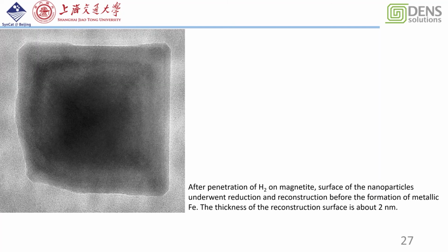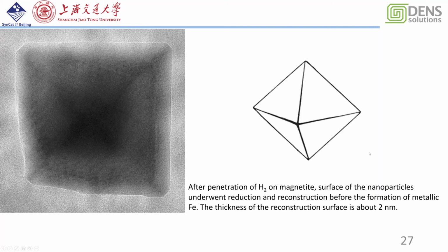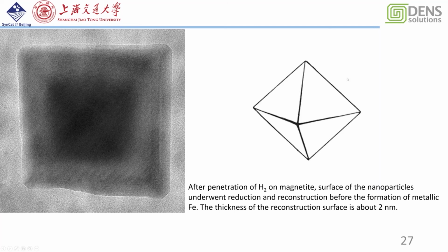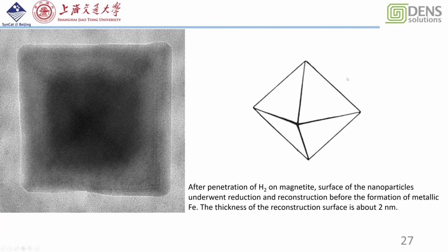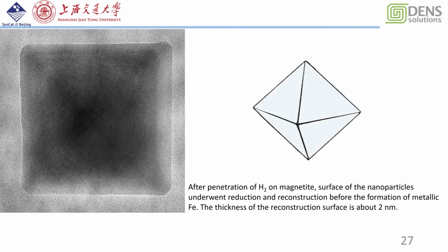So this is the octahedral particle. And during the reduction process, it looks like hydrogen penetrated inside the surface and formed the new species that completely covers the octahedral magnetite nanoparticle. Depending on the diameter change during the reduction process, the thickness of this new species is about 2 nanometers. And later I will give evidence to show why our assumption is right.